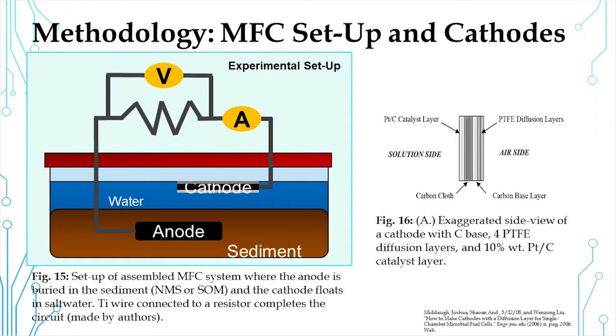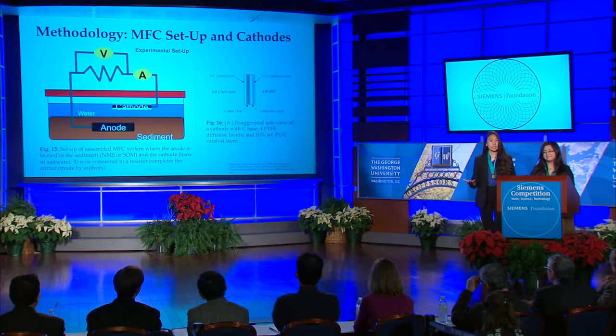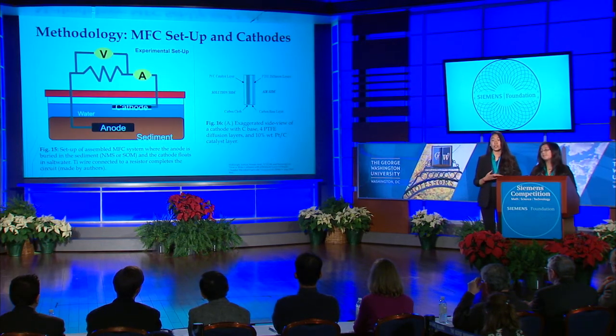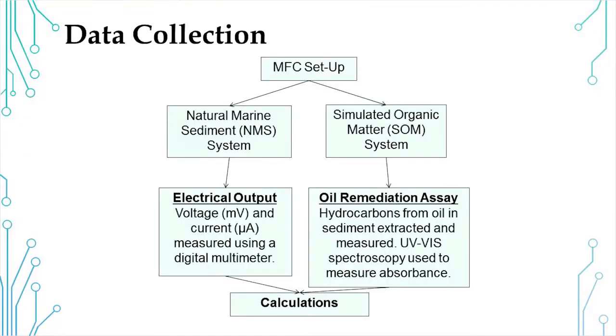The cathode was prepared with a carbon base layer, 4 PTFE diffusion layers, and a platinum carbon catalyst layer. Then the anode was submerged in the sediment where the bacteria existed, connected with a titanium wire, with the cathode floating on top. So we implemented the MFC in 2 different systems. We tested a natural marine sediment, which was collected from a benthos layer in a local saltwater area, to study how the MFC anode would react in a more natural simulation with mixed communities of bacteria. We also tested it in a simulated organic matter system to specifically study the oil degradation process, which contained oil-eating bacteria and oil.